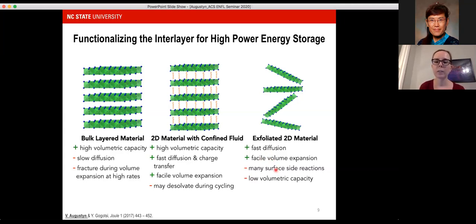But there are downsides. For example, there are also enhanced parasitic reactions, and the excess porosity means you have low volumetric capacity. In between these two extremes are materials that could be considered right in the middle, and perhaps would combine the best of both worlds. And it turns out that relatively little has been done to understand the structure, the dynamics, and the electrochemical mechanisms in such materials. And this has been the focus of what we're doing in our group.